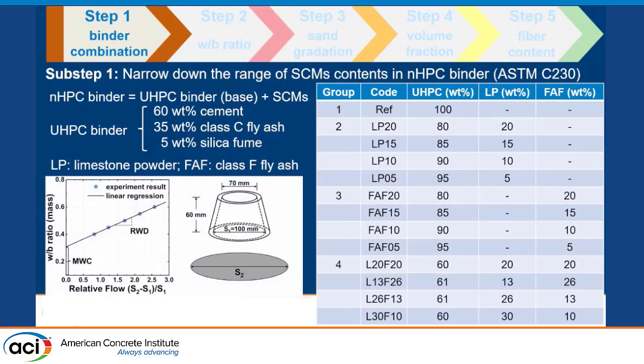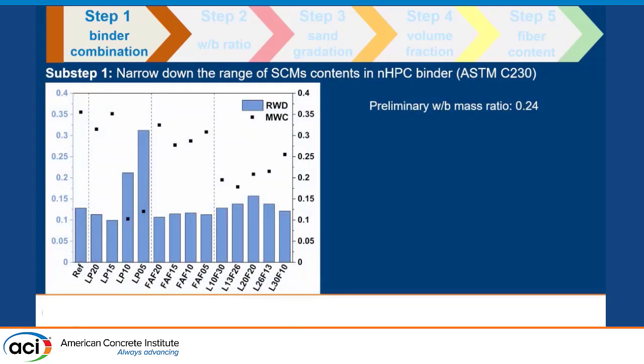And we're going to do the mini slump test to determine the linear relation between the relative flow and the water-to-binder ratio. As you know, the slope is RWD, which is short for relative water demand, and the intercept is known as minimum water content, MWC. By testing the fresh mixture with a preliminary water-to-binder ratio of 0.24, we can see the optimum range of limestone powder is from 5 to 10%, because a low MWC indicates a high packing density of the binder system, and a high RWD value indicates that the binder system is more robust to changes of the water-to-binder ratio.